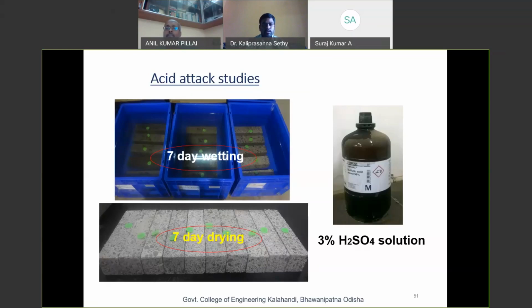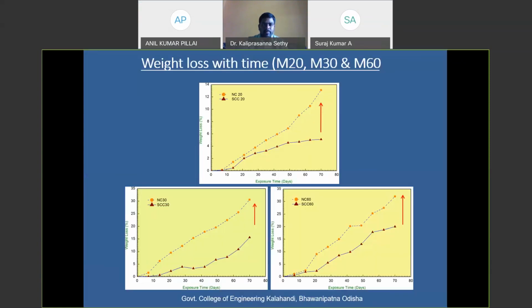You can see the test from the diagram. The test has a 14-day cycle. Of those 14 days, 7 days are for wetting and 7 days are for drying. Before wetting, we take the weight of the samples, and after 7 days we take the samples out of the acid solution, wash and clean them, and take readings of the weight loss of the samples. We repeated this every 7 days and obtained the weight loss values for all the normal and self-compacting concretes.